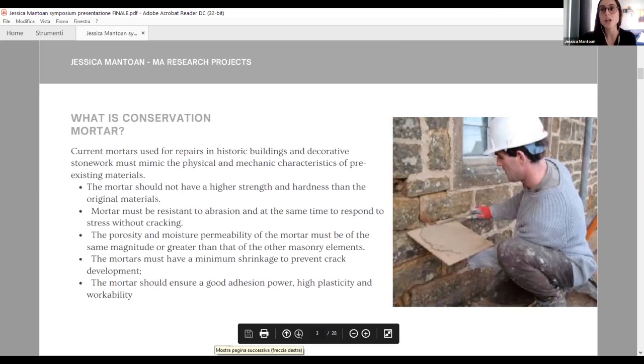on the other material. In order to achieve a sacrificial mortar, the mortar has to be prepared with a higher level of porosity and permeability with respect to the material on which it is applied, in order to be able to absorb all the water. The mortar must be less hard than the original material in order to mitigate mechanical stress, but most of all be able to absorb vibration. And finally, last but not least, mortar must be workable.